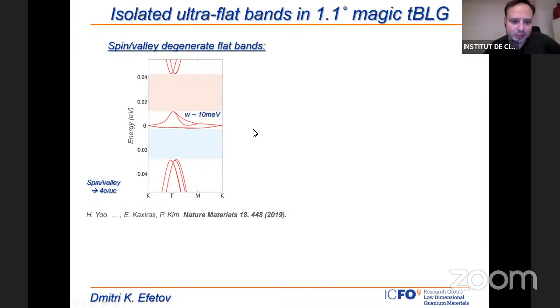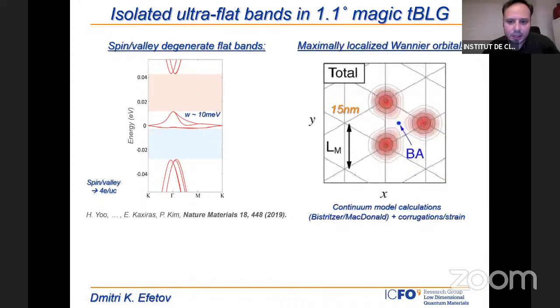So really zoomed in, we have those flat bands. They're isolated by energy gaps from the higher order bands. The bandwidth is very, very small, around 10 meV. And I also want to remind you that in graphene we have spin and valley degeneracy. So we have 4 degenerate electrons, spin and valley.